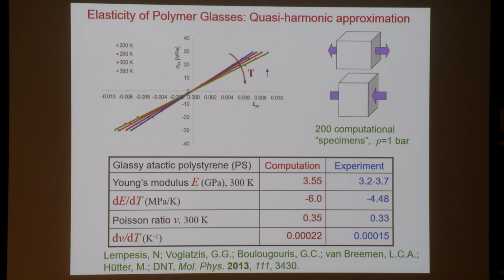One can also calculate elastic constants, taking into account the thermal motion as well. So to do so, one takes the model and subjects it to uniaxial tension or compression deformations in the x direction, having the y and z directions exposed to 1 atmosphere pressure. And from these deformations, one can calculate the stress-strain curve, which is shown here. And for the imposed stresses, it is linear. We're in the elastic regime. And one can see also the temperature dependence of the stress-strain relation. The higher the temperature, the softer the material becomes.